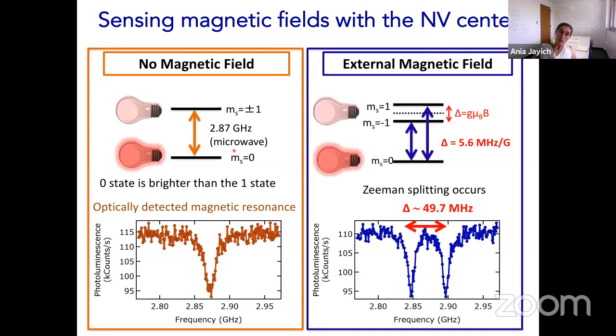NV. Now, in the presence of a magnetic field, the plus and the minus 1 states, through simple Zeeman effect, will split by an amount, again, that's quantitative. The splitting is exactly equal to g mu times the magnitude of the magnetic field, in this case, aligned along the NV axis. Okay, so with this 5.6 megahertz per Gauss splitting, we have a very quantitative sensor of magnetic